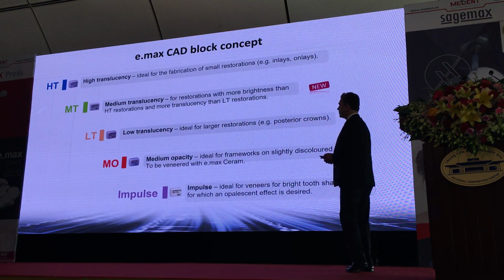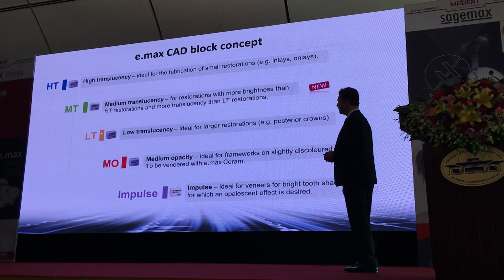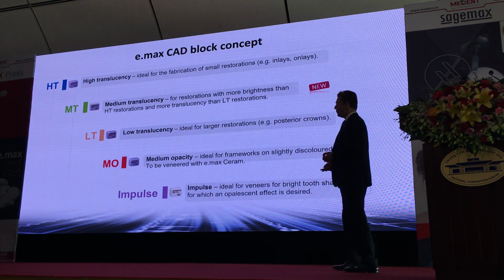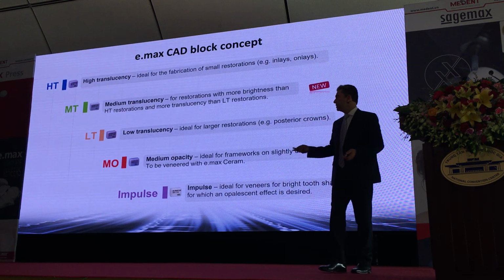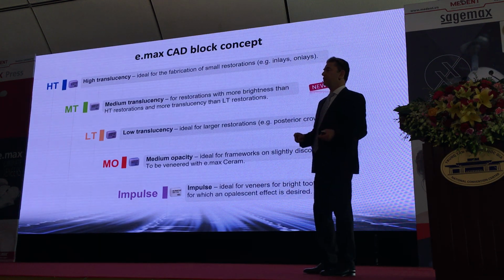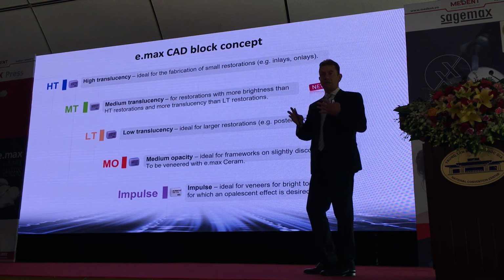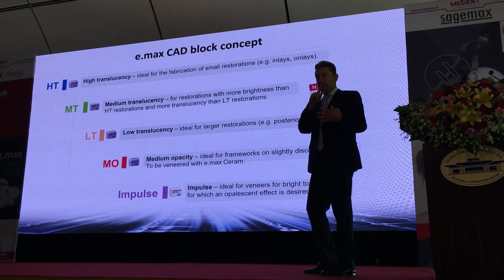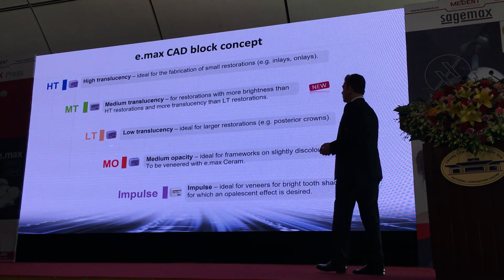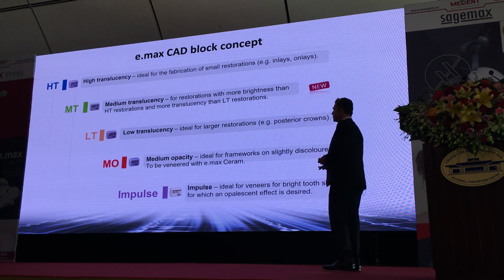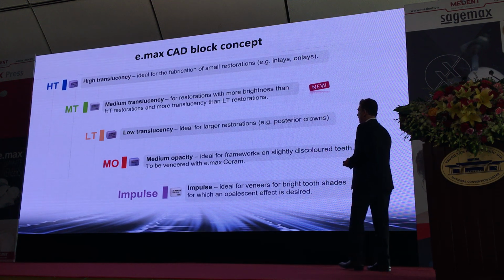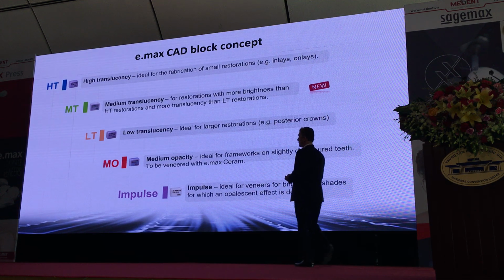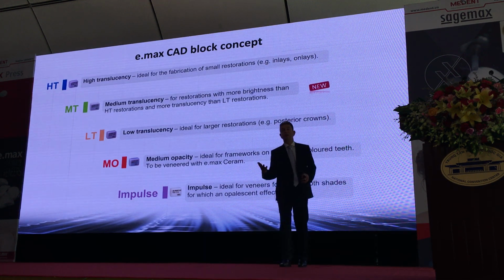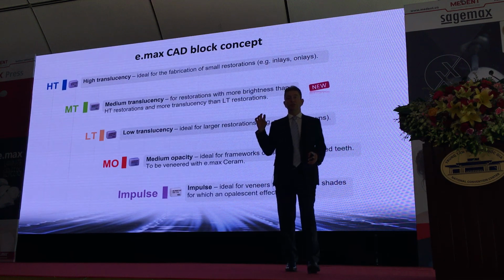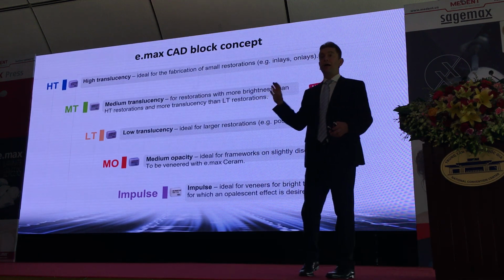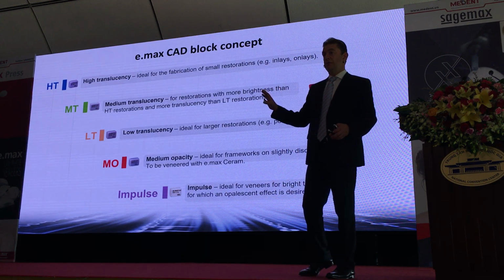So that's interesting. And then you can see here again, at a glance, the different translucency levels so that we can match every clinical situation, like HT, high translucency, which is very suitable for inlays and onlays and veneers where you have enamel all around. And you can use MT or LT for crowns and larger restorations. And the medium opacity, this one, is only for the lab. Let's say when you have a little bit of a discoloration, then the dental technician can use the MO block to block out the discoloration, right?